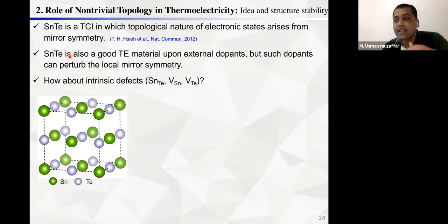But when we do the external doping, as I showed earlier, they dope the sodium atom, and with the doping of sodium, it makes a transition from non-trivial to trivial. When we do the external doping, it may perturb the local mirror symmetry. So to get a high ZT, we need to do the doping, but such doping can perturb the mirror symmetry. So how about intrinsic defects? Intrinsic defects mean we can do anti-site doping, or we can create vacancies, because such kinds of dopants are more compatible, and they preserve the original crystalline symmetry.